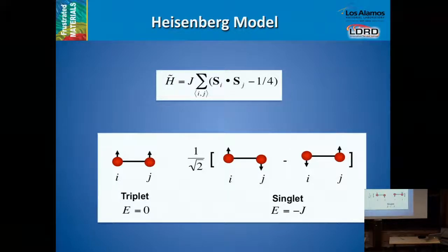If you think of the classical interactions between magnetic moments, that is the dipolar interaction, and dipolar interaction for the typical distance that you have in a solid, that is 3 angstroms, it will be a fraction of a Kelvin for typical magnetic moments. So to understand the existence of magnetic ordering at ambient temperature, you need to invoke quantum mechanics. And this is a simple example of how you can generate a strong spin-spin interaction via the Pauli exclusion principle. So Mott insulators, like the transition metal oxides, are normally described by this type of interactions, S dot S.